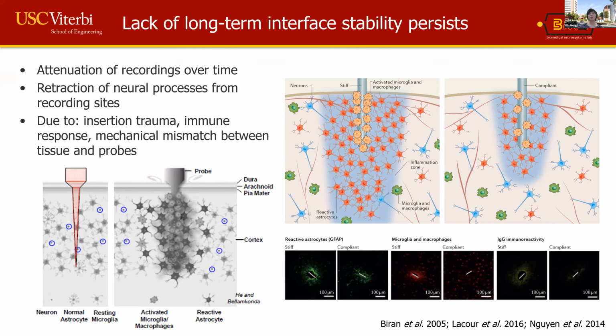But one thing that we are beginning to see more and more in the evidence in the literature is that by moving from very stiff materials that form the backbone of the probe that is placed into the nervous tissue to softer, more compliant ones, in general, you produce less of a severe immune response and can have a more stable device tissue interface over a longer period of time. And so this cartoon here and then the evidence down below, we're looking at staining in the bottom comparison between stiff and compliant kind of demonstrates that indeed there is some effect by moving towards softer, more compliant materials.